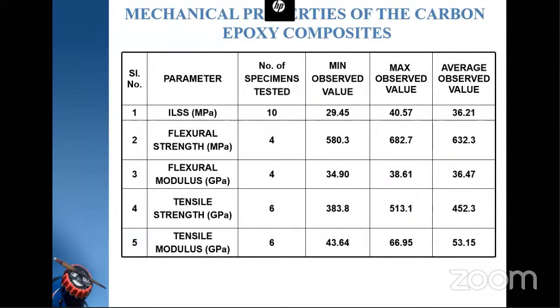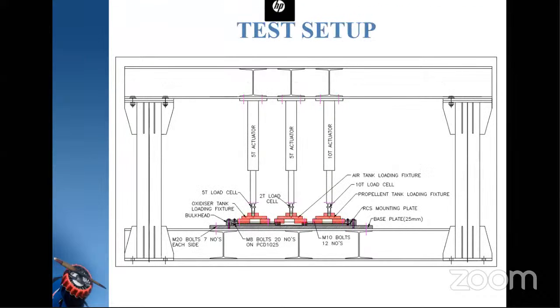These are the properties which we have measured by using the coupons: ILSS, flexural strength, flexural modulus, tensile strength, tensile modulus. These are the maximum number of specimens we have tested. Minimum value observed, maximum value observed, and the average value is given here. Then this is the load test which we have conducted in order to qualify this plate.